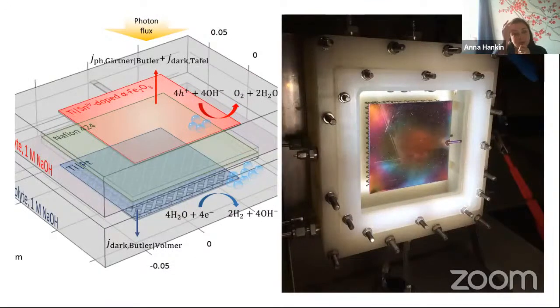So this is an example of a multiphysics model that we did in COMSOL Multiphysics, where we had one reactor that we didn't design because we thought, oh, this is the best design. We designed it specifically to investigate various macroscopic effects and to do some engineering studies. And so we had a photoanode and then just a normal cathode, and we applied a voltage externally to see what would happen. And we plugged in our microkinetic models for the two materials. So using the Butler-Volmer equation for the platinized titanium cathode, and then a modified form of the Gaertner-Butler equation, which predicts the flow of photocurrent as a function of potential. And then we divided the whole thing with the membrane, and we simulated the effect.